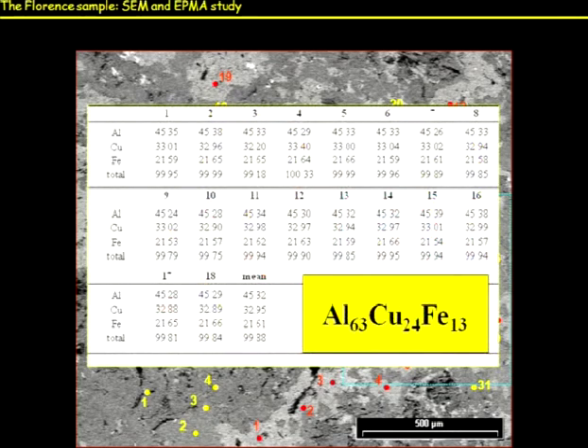Well, at the electron microprobe, these were the results of 18 analyses: aluminum, copper, and iron. This was the chemical composition when normalized to 100 atoms. When I saw this chemical composition, I was really shocked, I jumped on my chair, because this corresponds exactly to a synthetic quasicrystal proved to have forbidden symmetry in the lab. So I was already sure to have found the first natural quasicrystal.